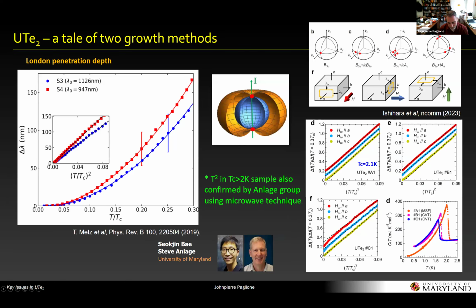The penetration depth is, of course, also a traditional experiment to study the gap structure. And with my colleague Steve Anlage down here, early on we did penetration depth measurements using his microwave impedance measurements, showing a nice quadratic temperature dependence on the two samples shown here, which is certainly consistent with a point node gap structure.